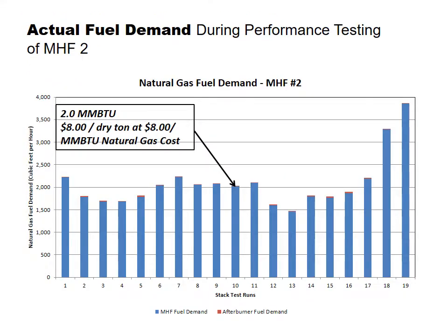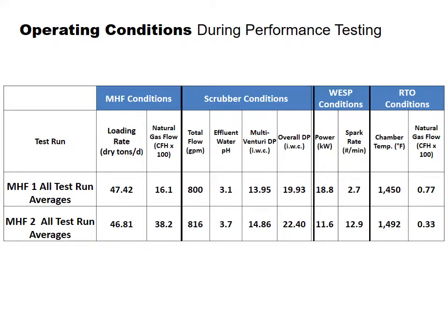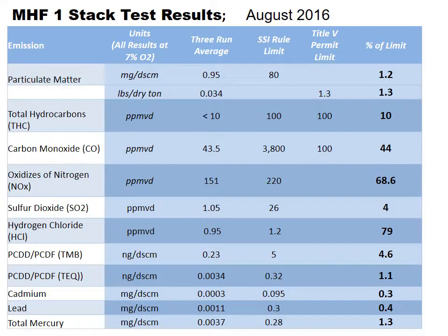We need to try to finish. Okay, multiple hearth furnace 2 was similar, used a little bit more fuel. The sludge wasn't as good. Performance testing, we loaded the furnace at its designed rate. We had a lower pressure drop because of these multi-venturis. The actual gas flow, we predicted about 2.0 million BTUs. We used about 0.5, about half of what we predicted in the RTO. Also, the gas flow at the furnace was good.